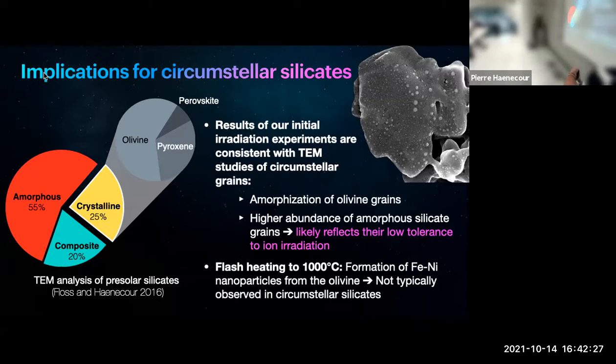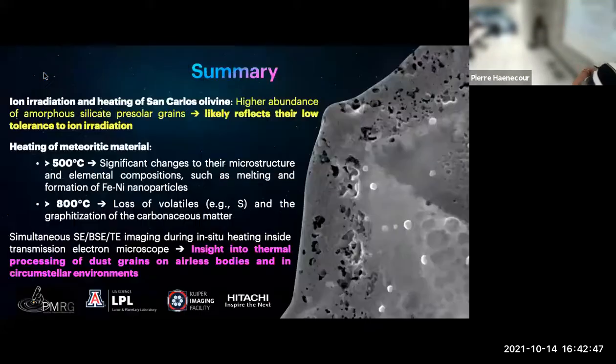And then we see that flash heating to 1,000 degrees leads to the formation of iron-nickel nanoparticles, which is not typically observed in those presolar silicate grains, which basically shows you that the mineralogy of presolar silicates is mostly reflecting irradiation in the stellar environment rather than flash heating or thermal processing.